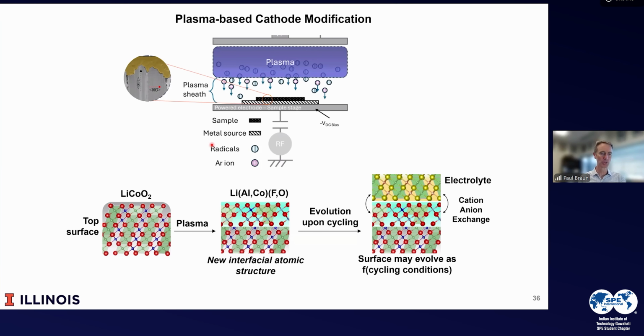So we're specifically interested in modifying the cathode. And so we start with lithium cobalt oxide. And what we discovered is that we can use a plasma method to introduce a small amount of aluminum and fluorine. And what that does is that creates a stable surface. And so the surface transforms from layered to rock salt. It becomes a disordered rock salt. And the combination of aluminum and fluorine in that layer increases the cycling stability significantly.